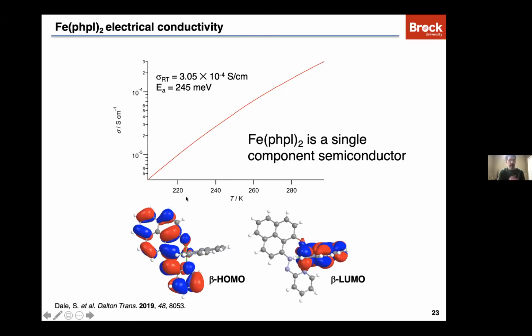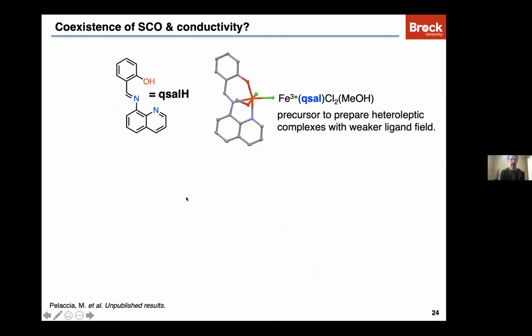So we've established now that we can have conductivity in these systems. We've established that we can have spin crossover and valence tautomerism. Now, can we put them all together in a single component material, which is ultimately what we're after? So one of the problems we have is that with many of these systems, the ligand field is too strong. And so we have low spin states of the metal, with no spin crossover properties.